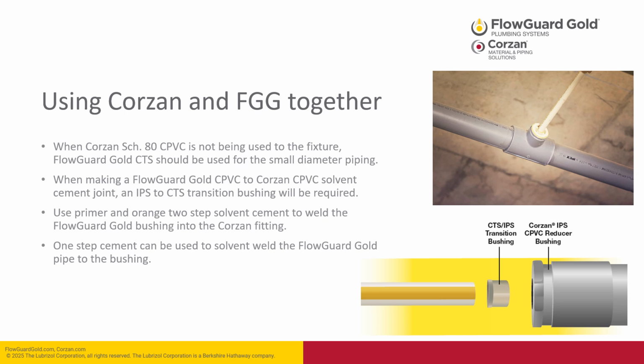Primer and orange two-step solvent cement will be used to weld the bushing into the Corzan fitting. One-step cement can be used to solvent weld the FlowGuard Gold pipe into the bushing. A good way to remember this is any time that there is a gray component receiving solvent cement, it requires a primer. If you are connecting the tan pipe to a tan bushing, no primer is required.